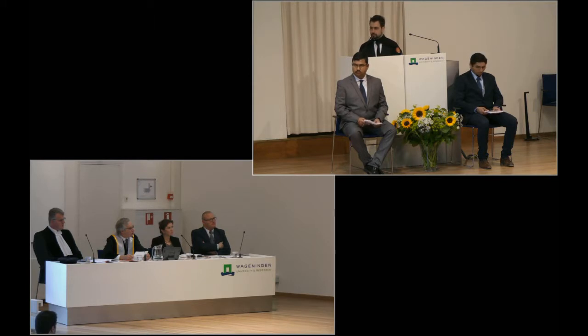Highly esteemed opponent, thank you for your comments and your question. The mechanism, I do not recall if I wrote it up. I think I perhaps wrote it in terms of text, but the copper 2 reacts with the hydrogen peroxide to form a copper peroxo complex that then abstracts one hydrogen from carbon, and any water in the vicinity, and even the peroxide itself, will react.